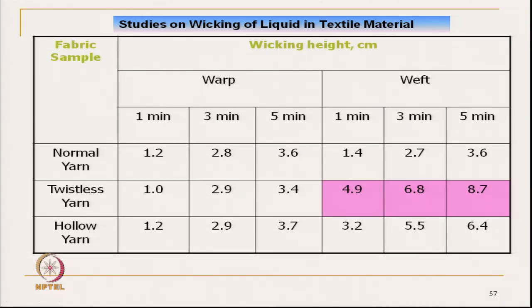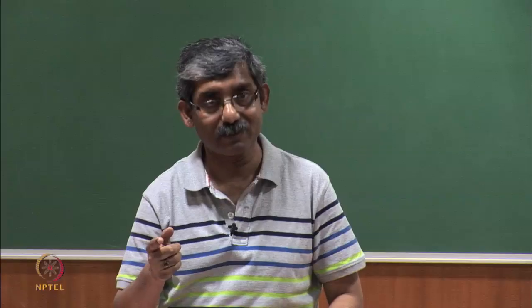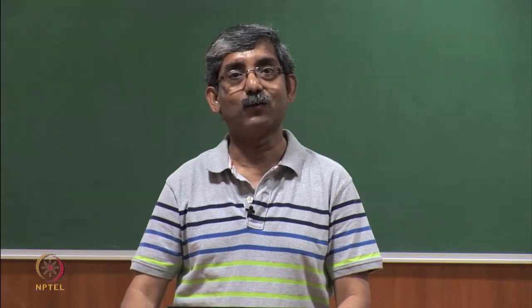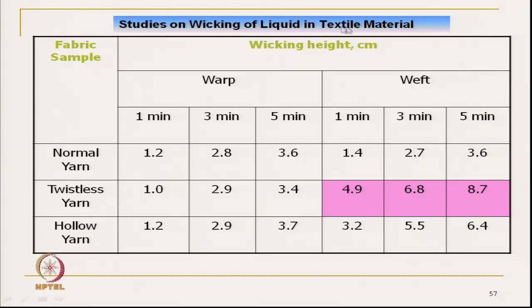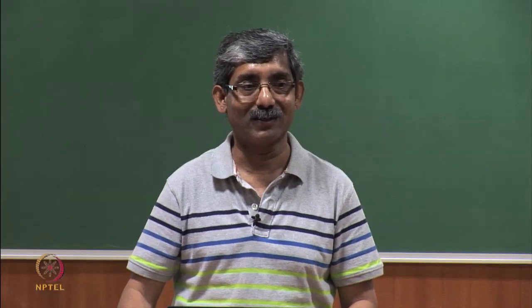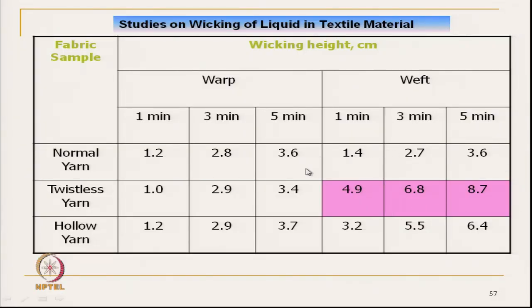And this phenomenon shows the tortuosity of the fabric. If the fibers are in a helix form in the yarn, as in normal yarn, it gives lower wicking height. But if the capillary channels are straight, that will give a very high wicking height. If we increase the twist, the capillary path will be a helix path, so the flow of fluid will be reduced. In the case of twistless yarn, the capillaries are straight, so the rate of wicking is very high and the wicking height is very high.